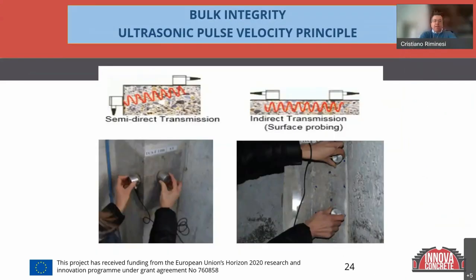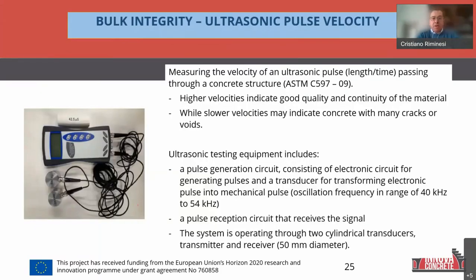Another device for understanding the hardness of the material, the concrete, and also the cohesion of the substrate, is the ultrasonic pulse velocity. In this case, this device involves the propagation of an ultrasonic wave in the material. The ultrasonic wave can propagate in the material if there is not a gap of air. In this case, the ultrasonic wave is stopped by the presence of air.